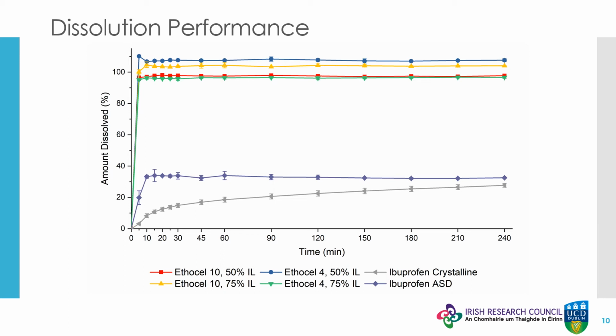grade. With the IL form of the drug, we found that it remained stable in concentrations ranging from 2 to 85% weight for weight in deionized water and simulated intestinal fluid for 2 years, with no evidence of crystallization or phase separation. At ratios above 50% weight for weight IL content, the dissolution media is now being solvated by the drug, which, in its free acid crystalline form, has a solubility of 0.068 mg per ml in deionized water. This is a remarkable improvement over ASDs, which only provide short-term stability and dissolution enhancement.